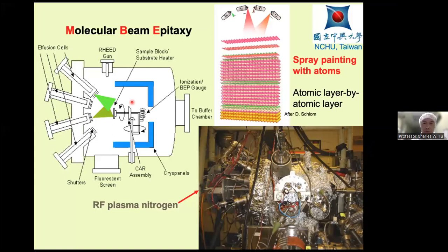When we want to grow material AB, we open the shutters of A and B. And for ABC, we open the shutters of A, B, and C. And then again, we close the shutter for C. So we can grow such a superlattice structure. Because the growth rate is about one atomic layer per second, and the shutter closing and opening is about 0.1 second, we can grow a very abrupt interface. For dilute nitride, we use an RF plasma nitrogen source because N2 is very stable, so we need to create a plasma to produce excited species.